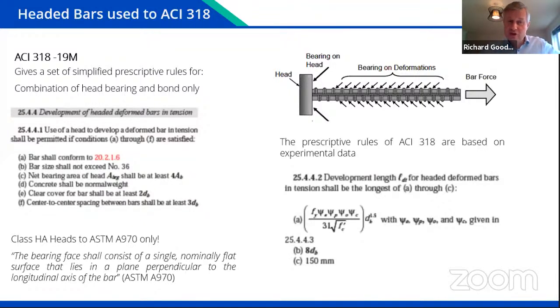And ACI 318 makes reference to ASTM A970 as the applicable product code for headed bars. And ASTM A970 says that a performance class HA head should be used to comply with ACI 318. It also states that the bearing face shall consist of a single nominally flat surface that lies in a plane perpendicular to the longitudinal axis of the bar.